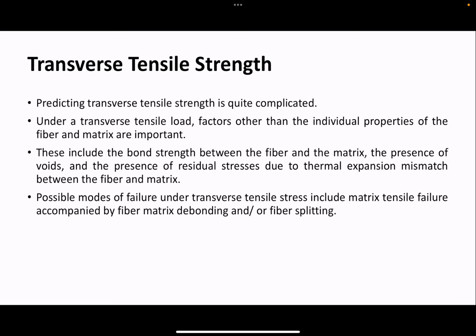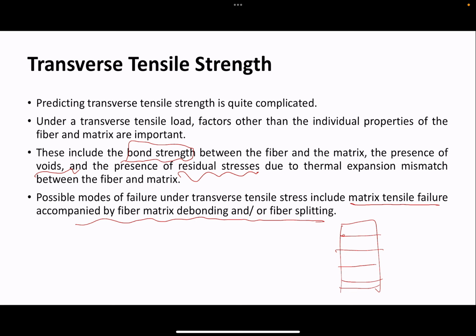So here the transverse tensile strength prediction by just analysis and models without doing experiments is quite complicated. Why? Because it's not only about the fiber and matrix. The bond strength plays a very important role. Are there voids? Are there residual stresses because of thermal expansion? There are a couple of factors that go into it. That is why predictive models or analysis of it becomes more complicated. But possible modes of failure are matrix tensile failure, understandable since it's direction 2, accompanied by fiber matrix debonding or fiber splitting. Meaning, what is fiber splitting? Because your specimen looks like this, right? So this fiber could split.